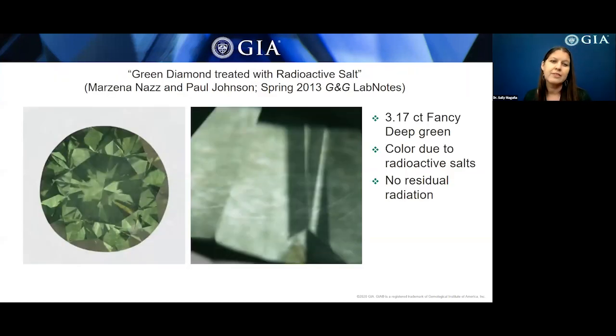Next up, this 3.17 carat round brilliant owed its fancy deep green color to irradiation from radioactive salts. On the right, a photomicrograph shows the diamond surface has a mottled effect due to shallow green radiation stains due to that physical contact with the radioactive salt. This method has mainly been used on polished stones, not so much on the rough.